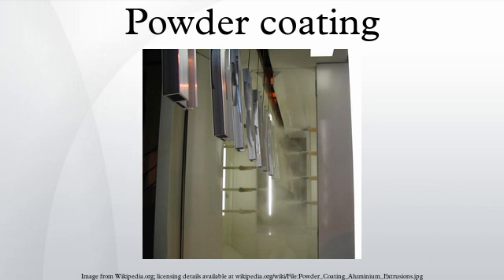As the film thickness is reduced, the film becomes more and more orange-peeled in texture due to the particle size and glass transition temperature of the powder. Most powder coatings have a particle size in the range of 30 to 50 µm, a softening temperature Tg around 80 degrees Celsius, a melting temperature around 150 degrees Celsius, and are cured at around 200 degrees Celsius. For such powder coatings, film buildups of greater than 50 µm may be required to obtain an acceptably smooth film. The surface texture which is considered desirable or acceptable depends on the end product.